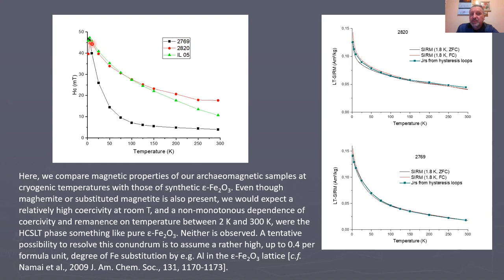No collapse of hysteresis loop, and also the remanence deduced from the hysteresis loop follow very closely the decay curves of the remanence given at 1.8 kelvin. So there seems to be quite a discordance between the observations done on synthetic epsilon iron oxide and on ceramic samples respectively.